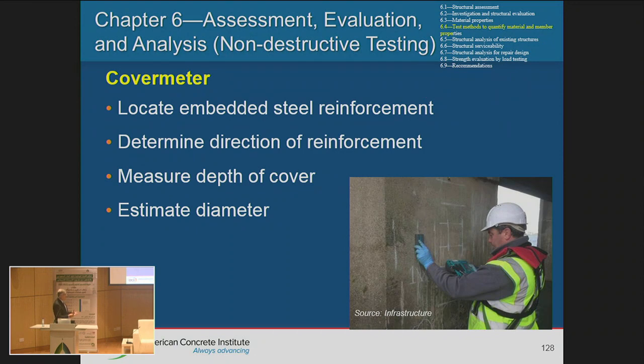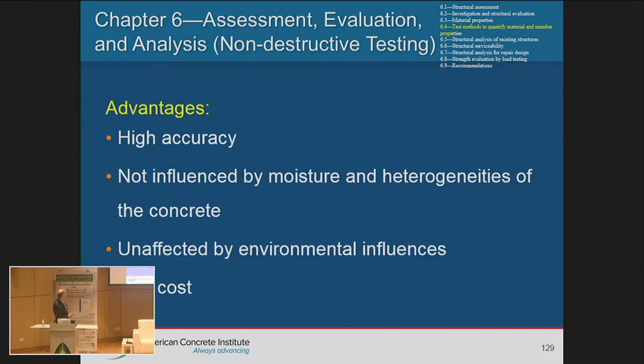So with the cover meter, it's not usually that easy to determine the bar size. Unless, for example, you chip a little bit, determine your depth, and find out what your bar diameter is, then based on that relationship, you can determine the other bar sizes by estimating. The advantages: it's high accuracy, not influenced by moisture, and it's low cost.